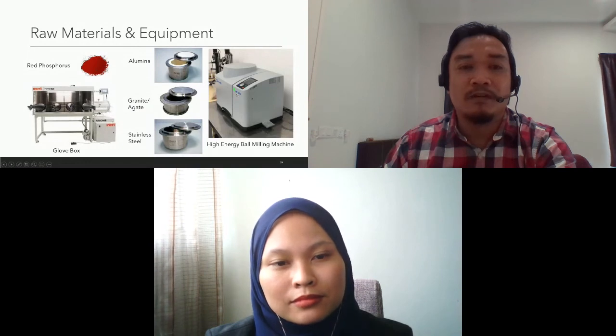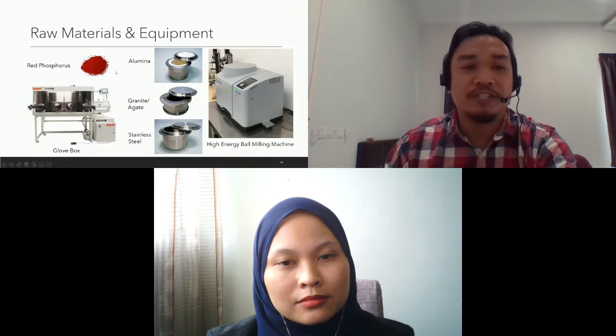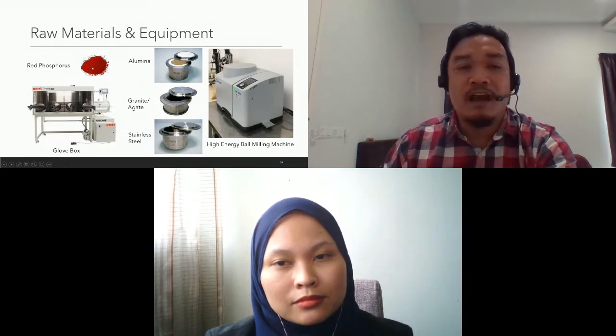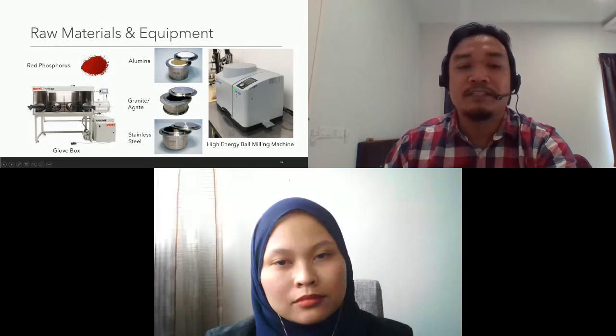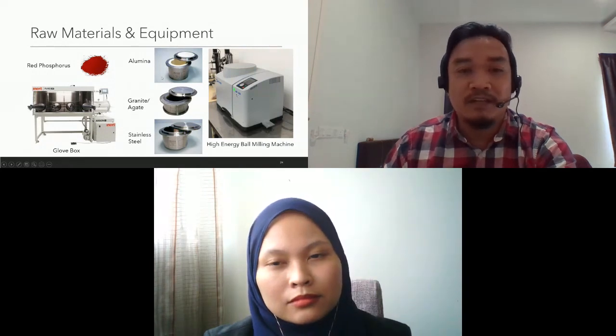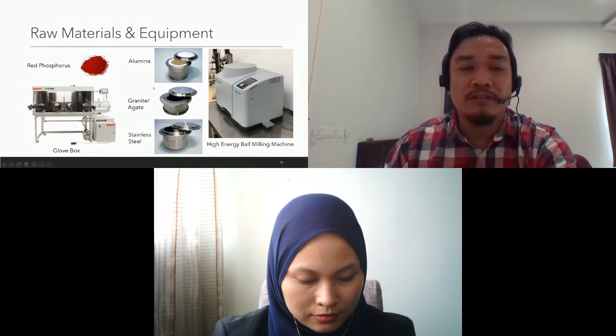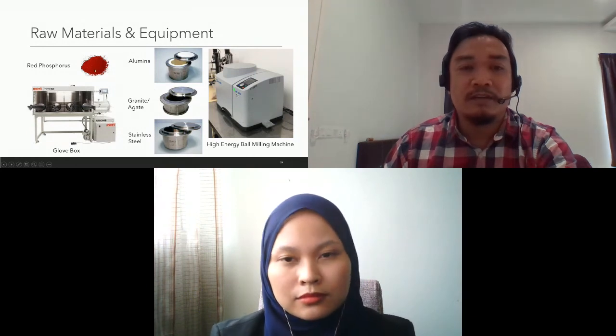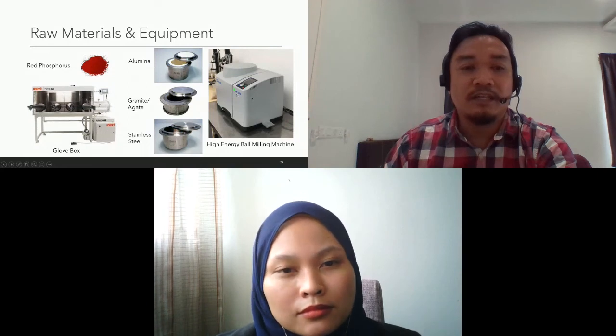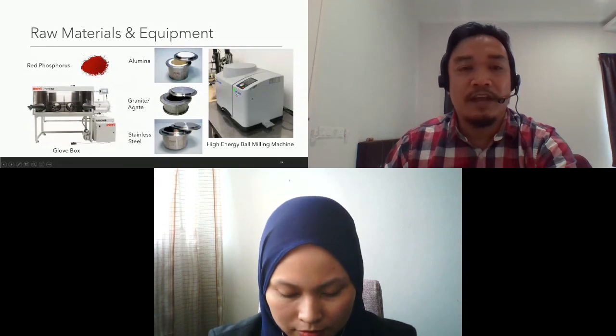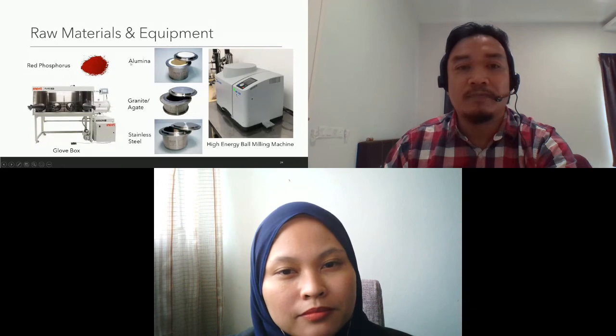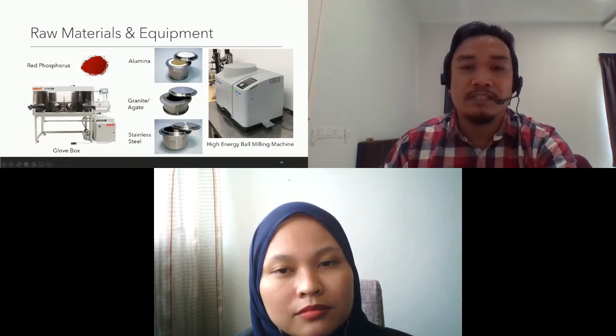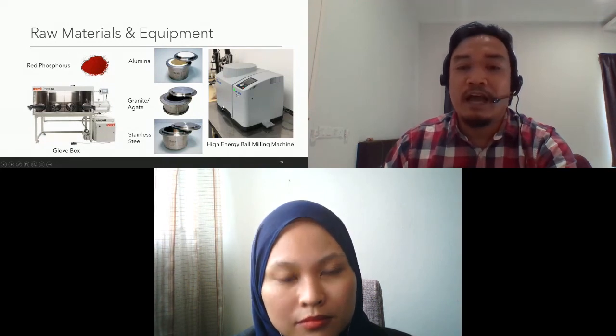We buy it from Sigma-Aldrich. We will insert the RP, red phosphorus, into three different kinds of jar: the alumina jar, granite or agate jar, and stainless steel jar. But in doing so, we will transfer the RP into the jar in the glove box, because we don't want the RP to react with the air. Once we insert the RP in the jar, we seal the jar and insert it in the high energy ball milling machine.